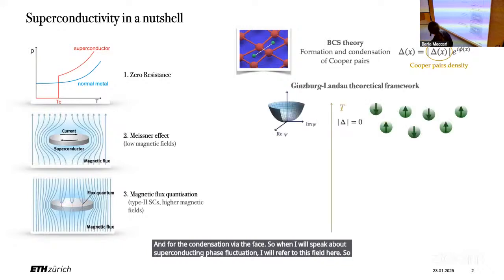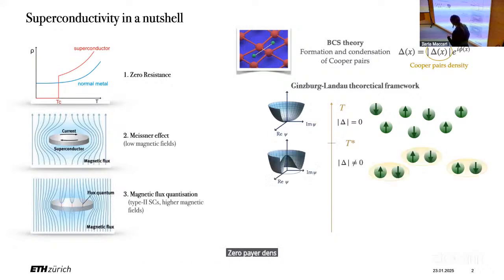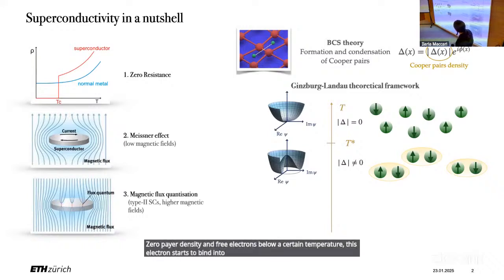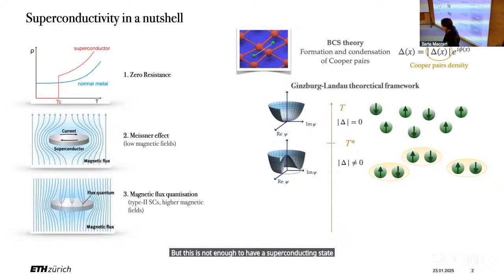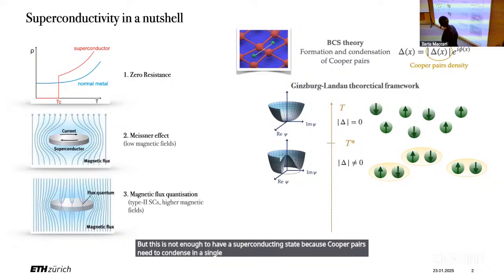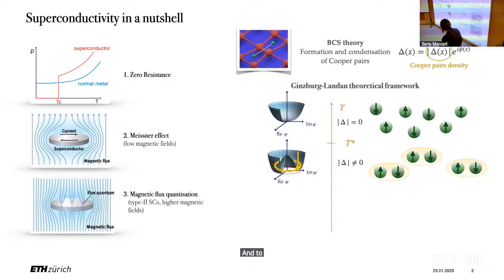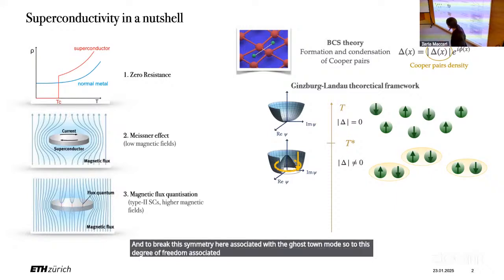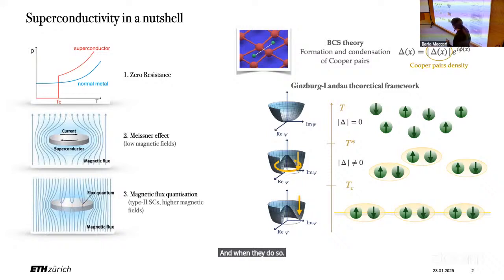So within this Ginzburg-Landau theory, the picture is more or less the following. At very high temperature, we don't have bound states, so we have zero pair density and free electrons. Below a certain temperature, these electrons start to bind into pairs, and the free energy landscape changes in this way. But this is not enough to have a superconducting state because Cooper pairs need to condense in a single quantum mechanical state. And to break this symmetry, associated with the Goldstone mode, so with the degree of freedom associated with the phase, when they do so, we have a superconducting state, essentially. So far, so good.